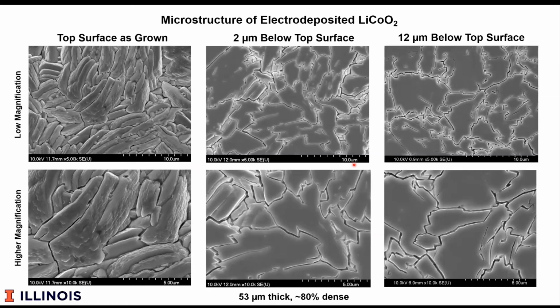So we decided to go and look much more closely at the microstructure of the electrodeposited LCO. What we're looking at here is the top surface. You've seen a number of other SEM images of this sort. This is both a lower and higher magnification. Here we are 2 and 12 microns below the surface. You can see these canyon or crack-like structures. These are not thermally induced cracks. They grow in this fashion.